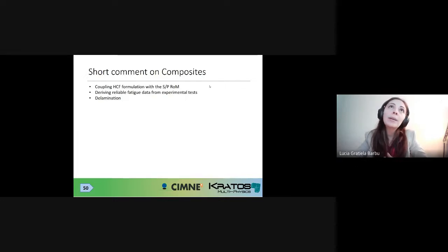We've dedicated effort to coupling the high cycle fatigue formulation with the serial-parallel rule of mixtures, which was also developed in our group back in 2008, I would say. Also, we've been dedicating effort to deriving reliable fatigue data from experimental tests. You'd think this is such a simple issue, but it's not, because it's very difficult to have S-N curves, for instance, for the high cycle fatigue domain, for the fiber and for the matrix, in order to isolate well the cyclic behavior of each component of the composite. This is very complicated to do, and Barbara, our PhD student, has been working on how to collect this data.